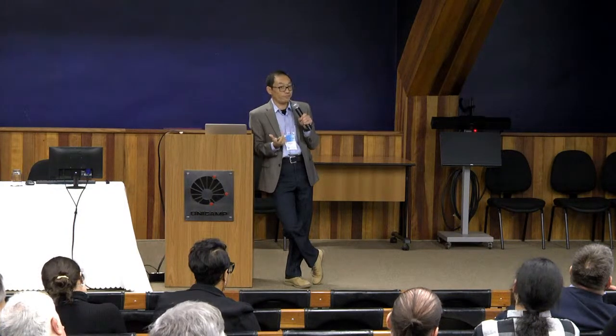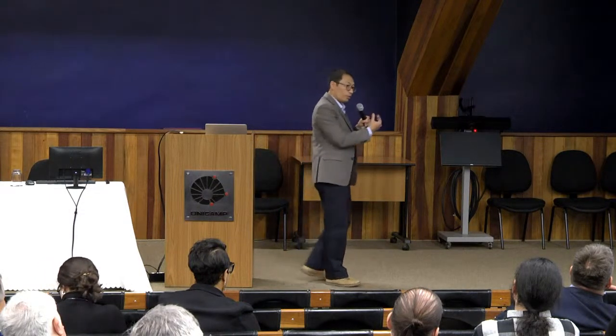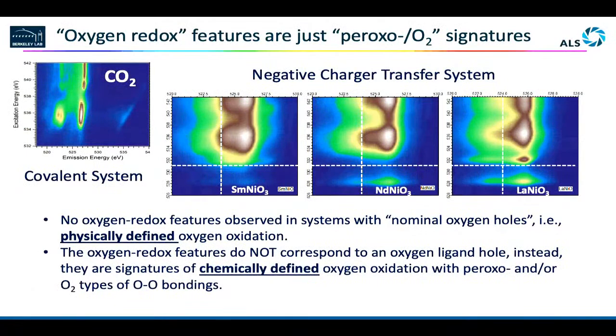Then we measured all kinds of these physically defined oxidized oxygen. We really don't see anything in those features because those features correspond to O-O bonding. And this is CO2, which we all know is highly covalent. It's very hard to say oxygen is 2- in CO2 because it is highly covalent. And if you look at the negative charge transfer systems, we measured a bunch of different thin film materials. We never see the crossing point and the elastic peak here. They're supposed to show that kind of feature.